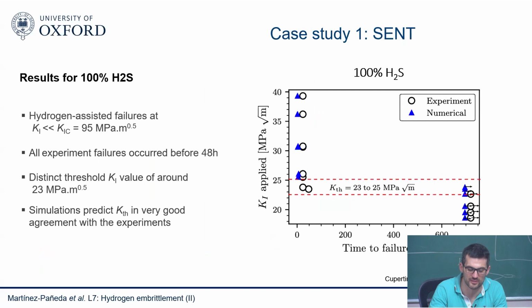This is the 100% H2S. So this is the K applied and the time to failure. So this is the experimental load, so you see that if you apply a sufficiently low load, no failure happens after 720 hours, which is the limit, then they stop the test. So these arrows mean I stopped the test because failure wasn't happening. And you can see that both experiments and modeling seem to agree quite well. So if we have a big applied load, then fracture happens in both the experiment and the model, more or less at the same time.